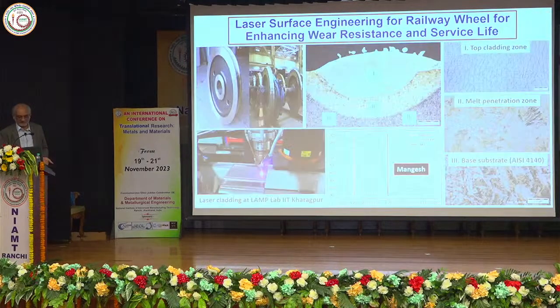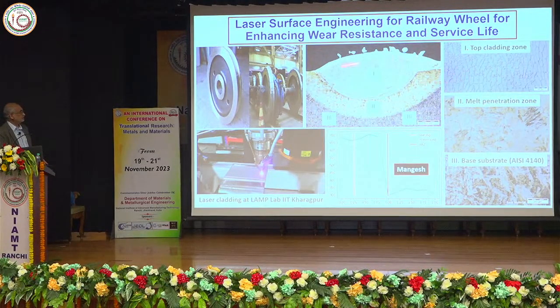So that's the idea. A similar effort is done by Mangesh, and he wants to take care of these wheels, the railway wheels and pulley wheels, where cracks and erosion or wear onto the surface is very common, and he wants to prevent that by having a harder coating. So this is a signature in terms of hardness variation — one can make it sharp, or one can make it shallow, graded.